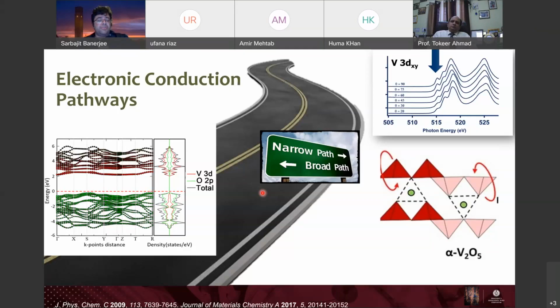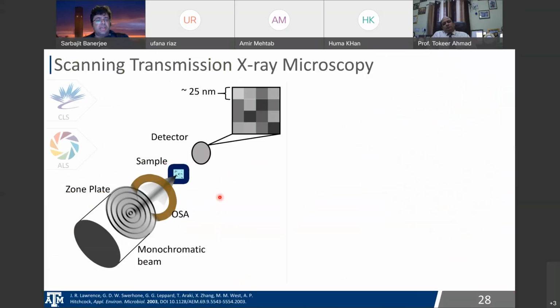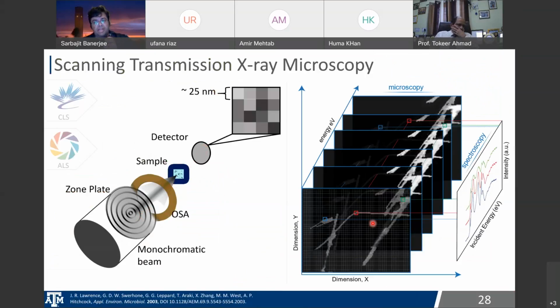Now when we started doing these experiments, looking at this material, we understood what the problems were. We've got a substantial challenge both in terms of ionic diffusion, the large changes in coordination number, and also a substantial challenge in terms of electron conduction. In my group, we do a lot of X-ray microscopy. It's a fairly sophisticated tool. It's work done at the Canadian Light Source, the Advanced Light Source. And what we do is we can use a very finely focused X-ray beam and just use that to image samples. And this is an example of how you image it.